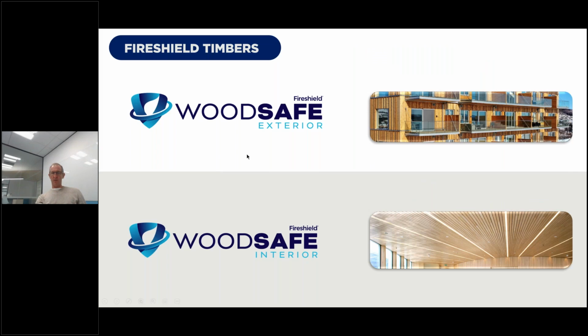As I said before, our exterior facade system for Type A is wood safe exterior. We're very excited about it. It's cedar only. And then obviously we've got a lot more timbers also available in wood safe interior dry space. But there's about 10 to 12 timbers that are tested. They all have to be tested, unlike an intumescent where we can put the intumescent onto a timber substrate that is a minimum thickness and density. With these timbers, we have to actually have tested the species, which we do.